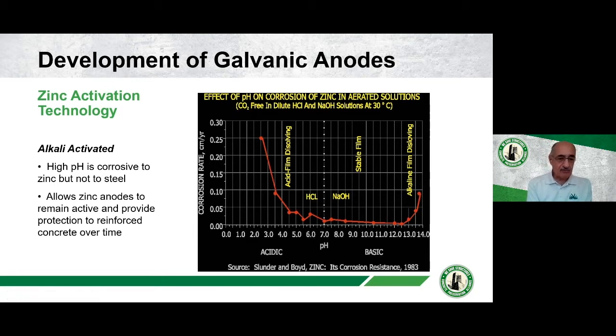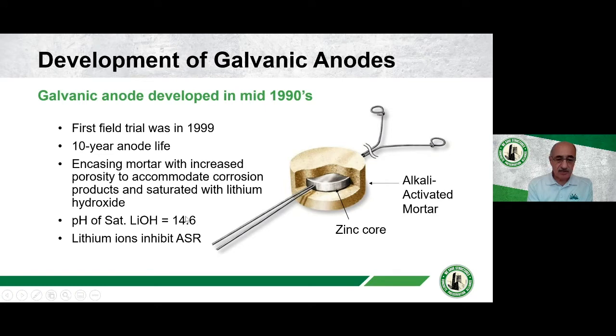And the way that we did that was actually to use saturated lithium hydroxide. Saturated lithium hydroxide has a pH of 14.6, and being saturated means it maintains that pH for as long as saturation exists. So that was our starting point. Lithium hydroxide is the activator, encased in encasing mortar, but we also made sure that the mortar itself was highly porous, so that it can contain the corrosion products that were coming out of the zinc metal.